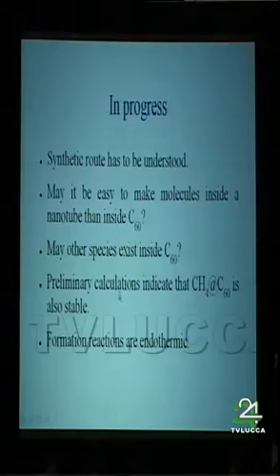I mean, in the literature, you read about metal ions or very small molecules. But for example, what I haven't found, and so I've run preliminary calculations, is, for example, methane inside C60. I think in the literature I tried methane attached outside to C60, but not inside. And calculations indicate that also the species CH4 at C60 is stable. And while for the metal hydrides, the simple energetic balance indicates that the formation reactions are endothermic, for CH4 at C60, I mean, it seems this is at least isoenergetic to the separate items, CH4 and C60.